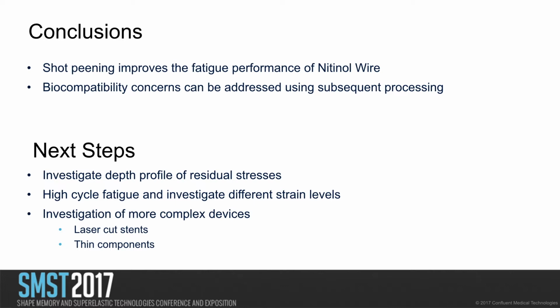So the conclusions that we draw from this is that shot peening can definitely improve the fatigue performance of nitinol wire. It also, if processed properly after peening, can meet biocompatibility concerns that we face here in the medical device industry. Some of the next steps: we'd like to investigate the depth profile of those compressive residual stress layers, and ways to do that include higher energy X-ray diffraction and neutron diffraction measurements. We would also like to perform higher cycle fatigue measurements, so go above 1 million cycles and see if these fatigue benefits are long-lasting or if they tend to taper, and also investigate different strain levels.